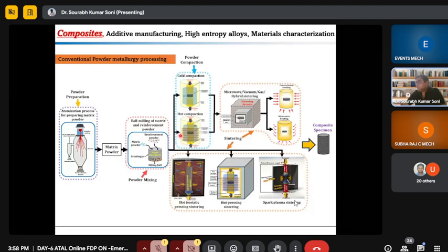Apart from stir casting, this is the conventional powder metallurgy processing. I'm highlighting the word conventional because most researchers are using this conventional powder metallurgy. First step, powder atomization by gas atomization or water atomization. In gas atomization, we will achieve spherical powder. In water atomization, not very spherical, but random kinds of particles.